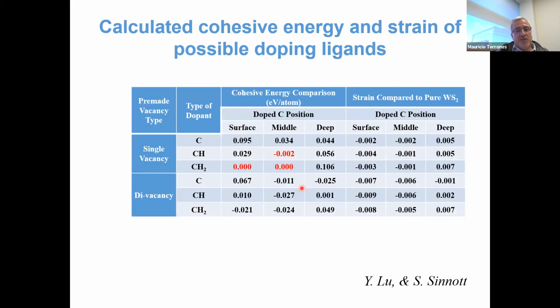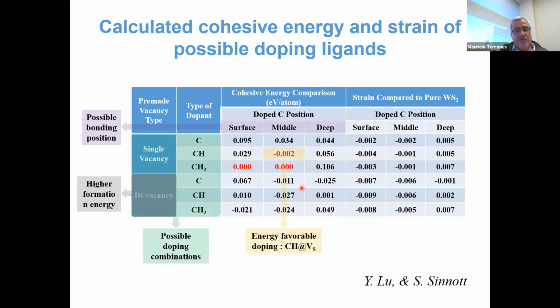With Susan Sinnott's group, we asked, what are the possibilities that we can find? Can we find carbon substituting into the sulfur vacancy? That is energetically not very favorable. What is more favorable is when you have this negative energy, so it's the carbon hydrogen. A carbon hydrogen unit is more stable sitting in the sulfur vacancy, or even the CH2 unit is similar in stability.